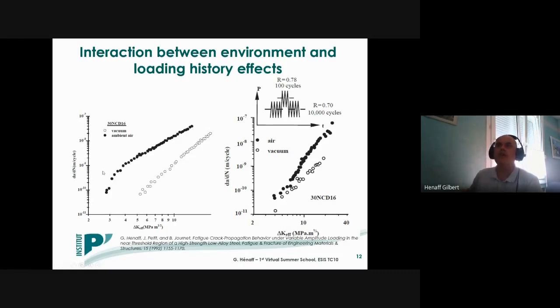And you can see that, especially at low delta K value in the near threshold region, we have quite a large fatigue crack growth rate enhancement with about a factor 30 on the crack growth rates. And this fatigue crack growth enhancement tends to reduce when the delta K value is increased.